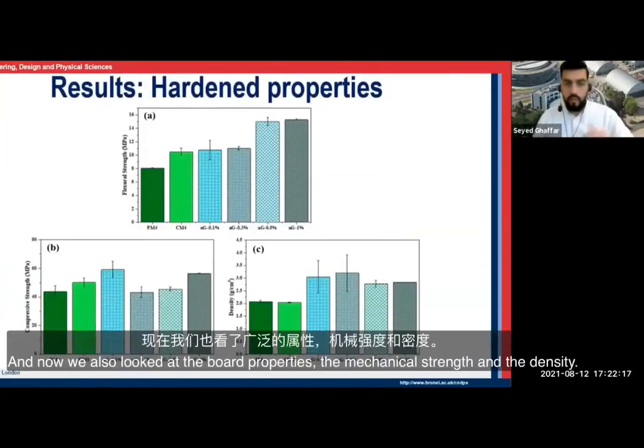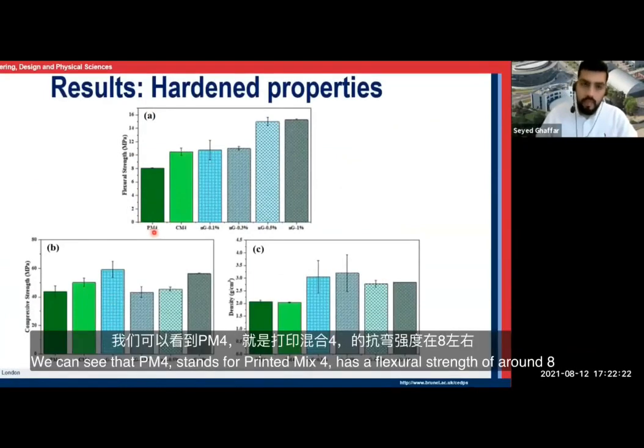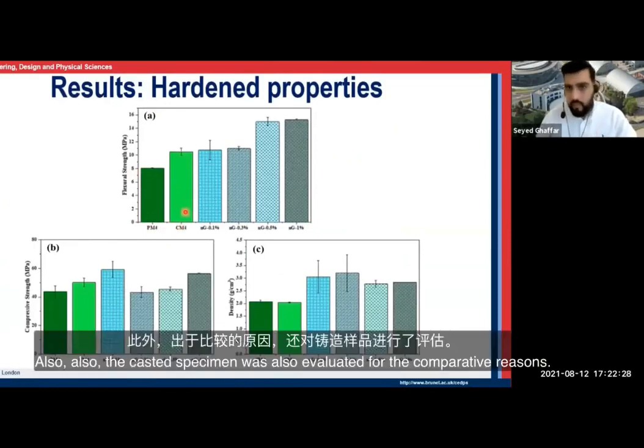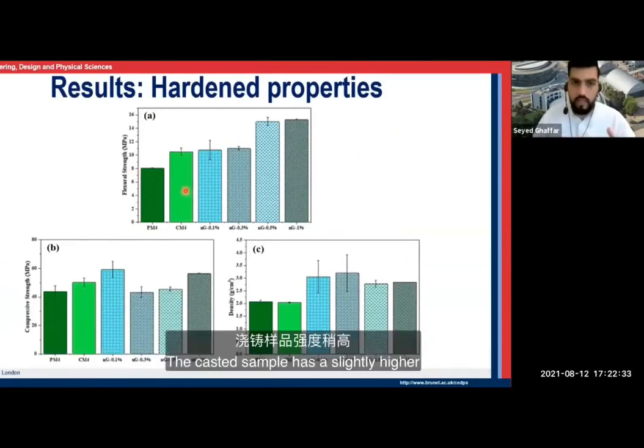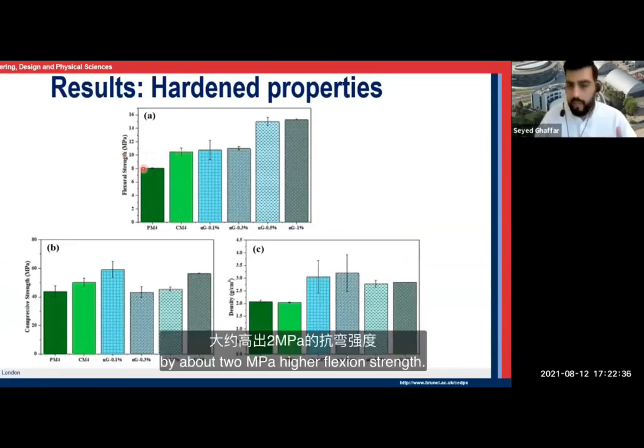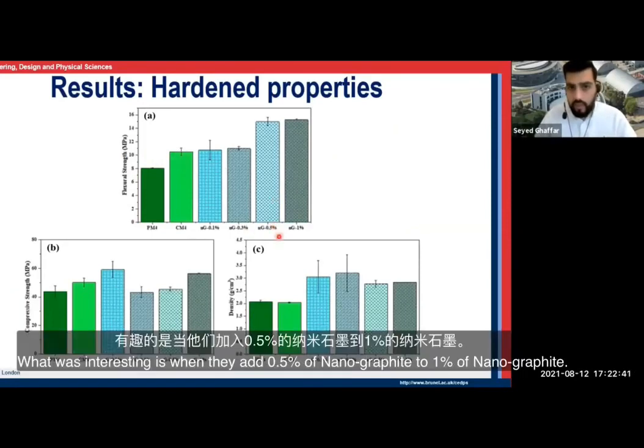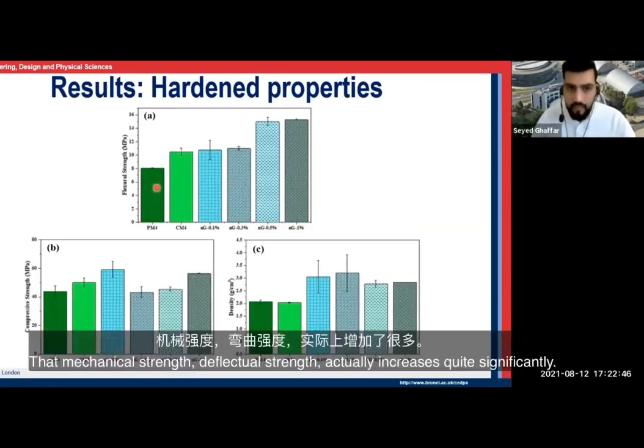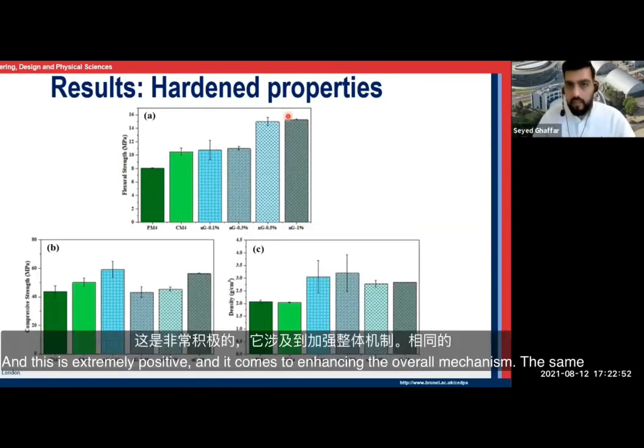And now we obviously looked at the bar properties, the mechanical strength and density. You can see PM stands for printed mix 4. It has a flexural strength of around 8. Also, the cast specimen was evaluated for comparative reasons. The cast sample had slightly higher flexural strength, by about 2 megapascals. But what was interesting is when we add 0.5% or 1% of nanographite, the flexural strength actually increases quite significantly. And this is extremely positive when it comes to enhancing the overall mechanical performance.